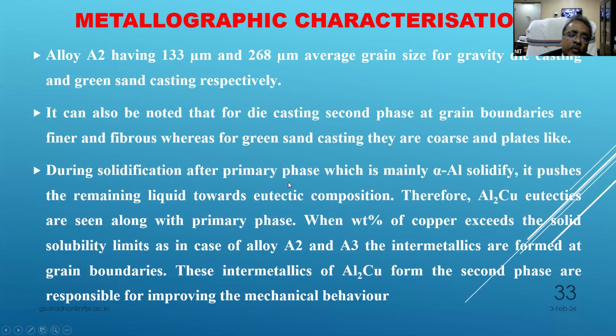During solidification, after the primary phase, which is mainly alpha aluminium, is formed, the remaining liquid is pushed towards the eutectic composition. Therefore, Al2Cu, the eutectic, is seen along with the primary phase. Now, the weight percentage of copper exceeds 8%, that means the alloy exceeds the solubility limits in the case of A2 and A3. The intermetallics, Al2Cu, formed at the grain boundaries form the second phase, improving the mechanical behavior.